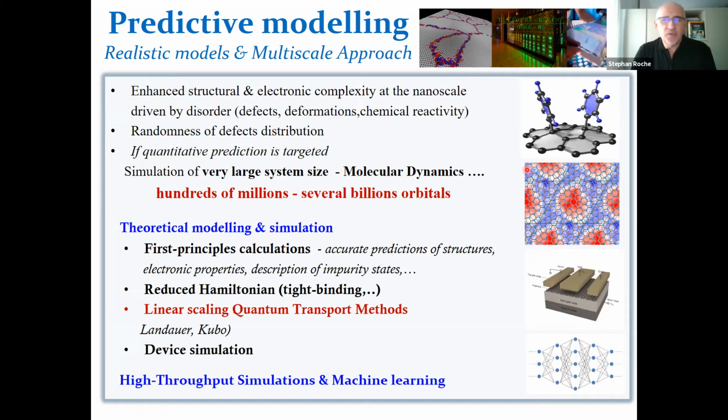You capture the most essential part of the Hamiltonian from a comparison between, let's say, a tight-binding model and first-principles band structures for small unit cells. Then you investigate larger and larger unit cells, and also the effect of single defects, and find a way to extrapolate on the tight-binding model. This is very interesting, but it's not enough